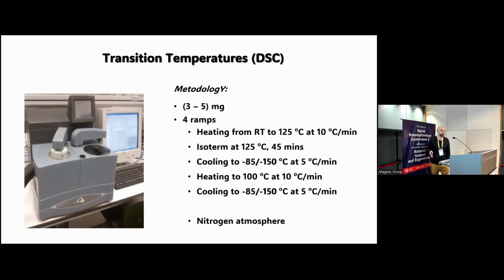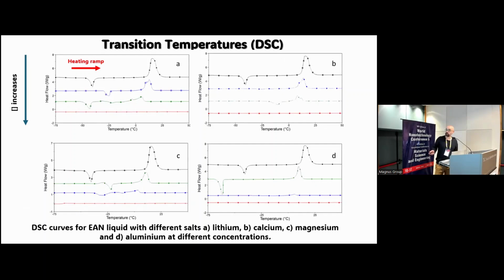We have also measured and determined the transition temperatures of this ionic liquid and these mixtures in a differential scanning calorimeter with this methodology under nitrogen atmosphere. You can see the temperature range is about minus 80 to 100 degrees. You can see here in black the pure ionic liquid. It presents quite good crystallinity behavior. You can see here a cold crystallization followed by a melting. And you can see here the concentration increases of lithium, calcium, magnesium, and aluminum.